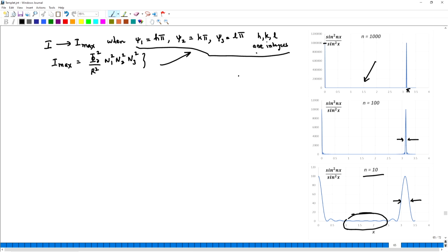And just before I continue, this peak broadening, you may have known about this, that there would be a widening of the peak for when the crystals are of very small size. So, small crystallite size will produce peak broadening, that just comes out of this analysis. So, let me write these conditions now in a different way. So, we know that psi 1 equals 2 pi upon lambda times the dot product between the scattering vector S and the unit cell vector A,